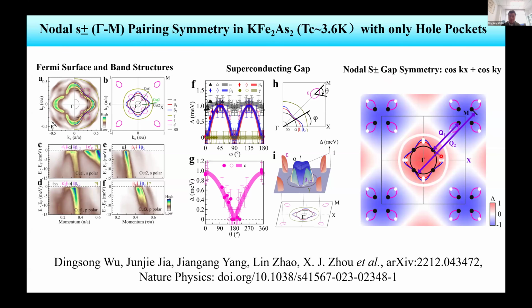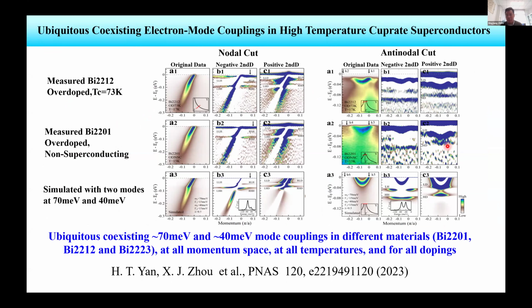Also, by using this ARPES, we gained some new insights on the many-body effects in cuprates. Previously people knew we have the famous 70 meV kink in bismuth samples and other samples, but we also have the 40 meV antinodal kink that is only observed in bismuth 2212 in the superconducting state near the antinodal region. But from our latest measurements, we found that in another direction, in both bismuth 2212 and 2201, we can see the coupling of electrons with both modes, 70 meV and 40 meV.